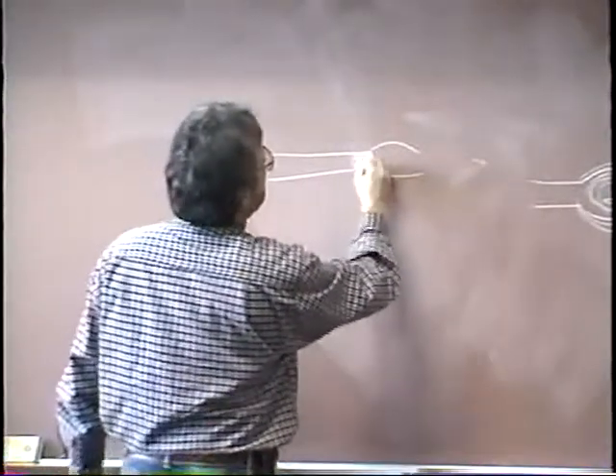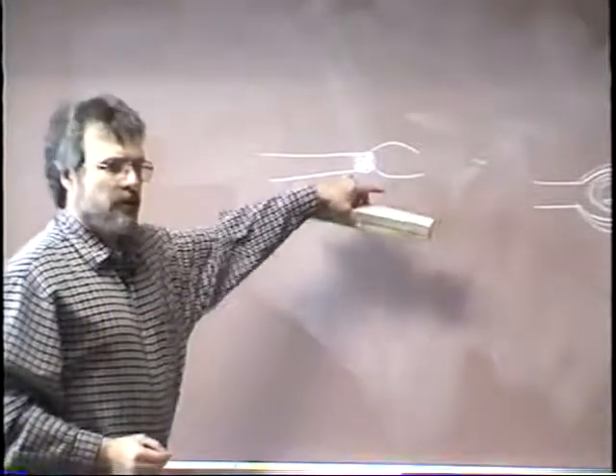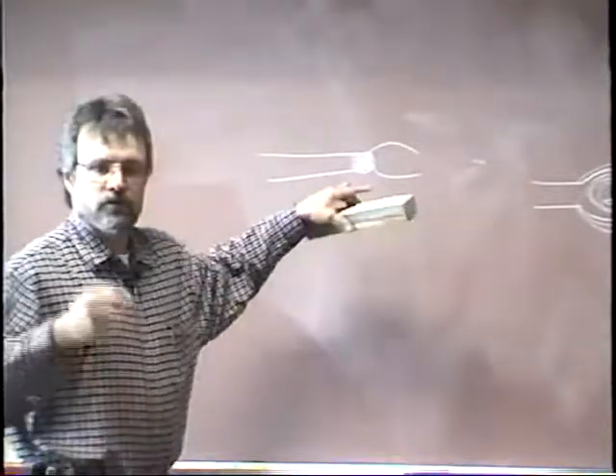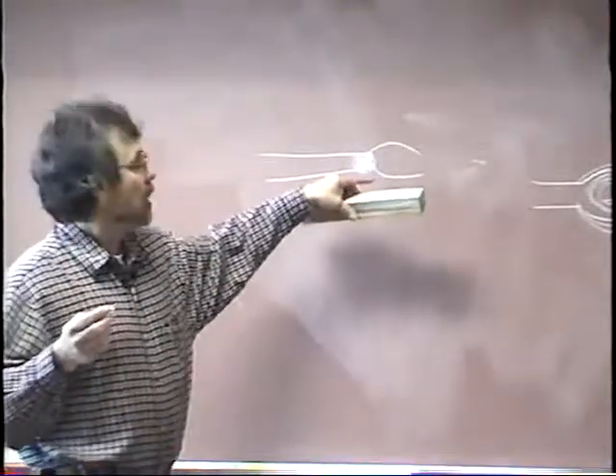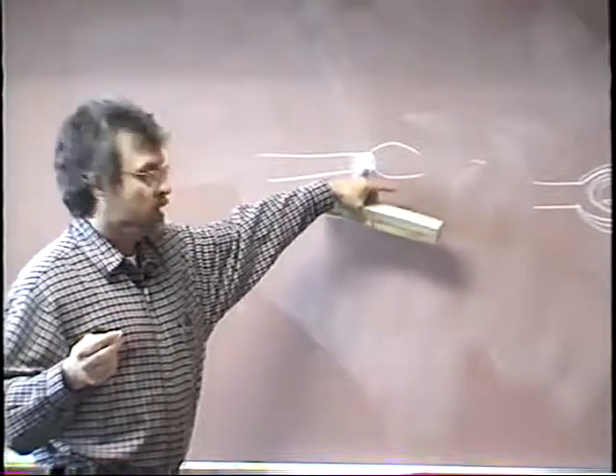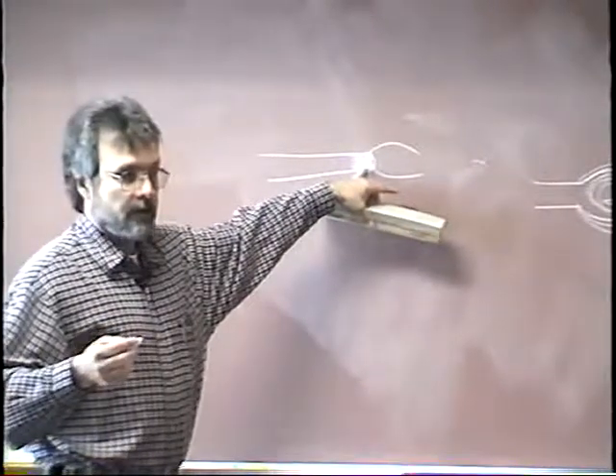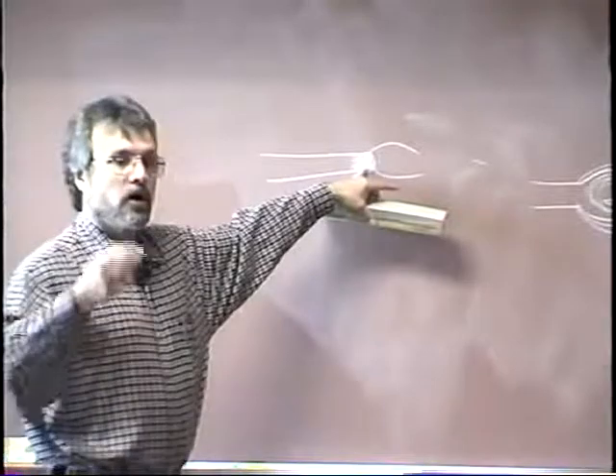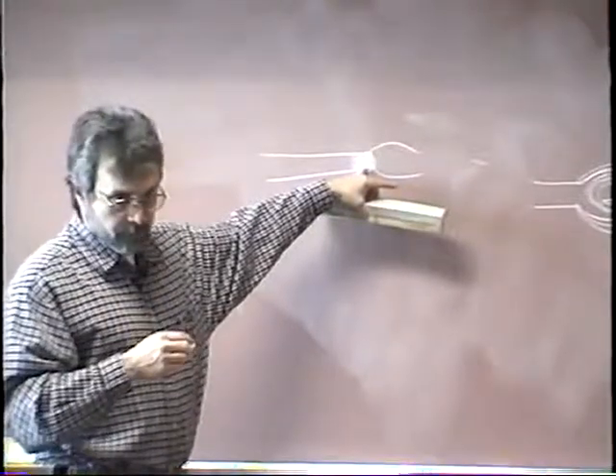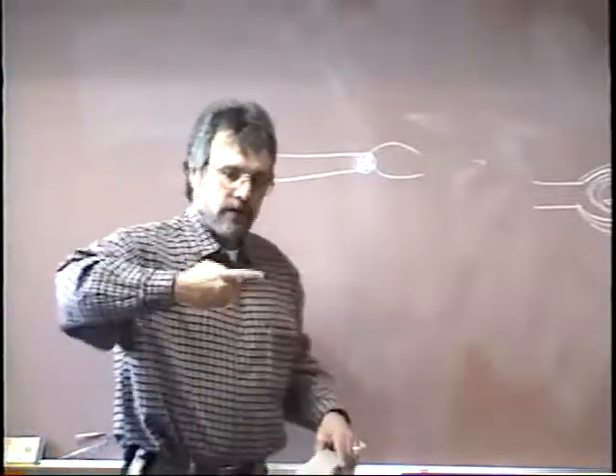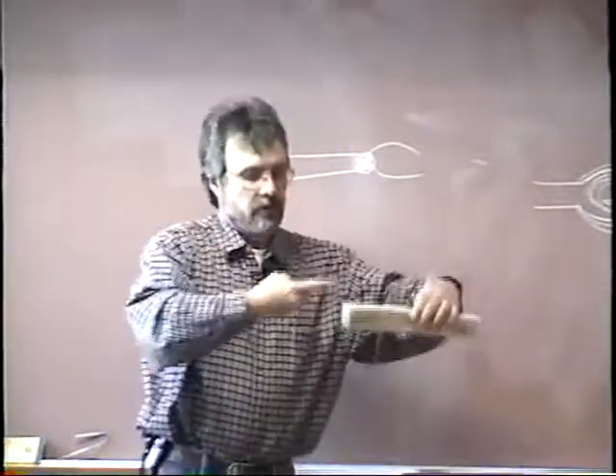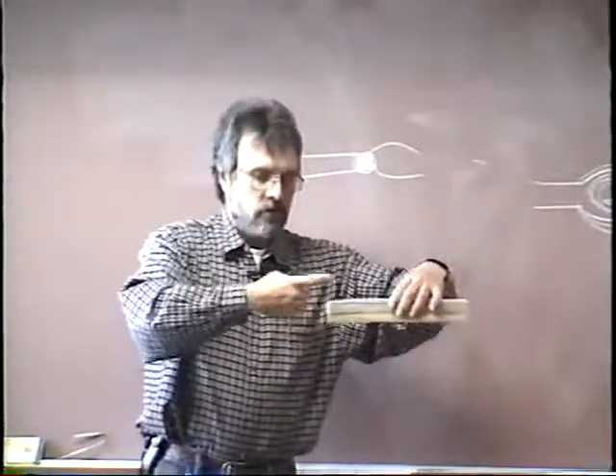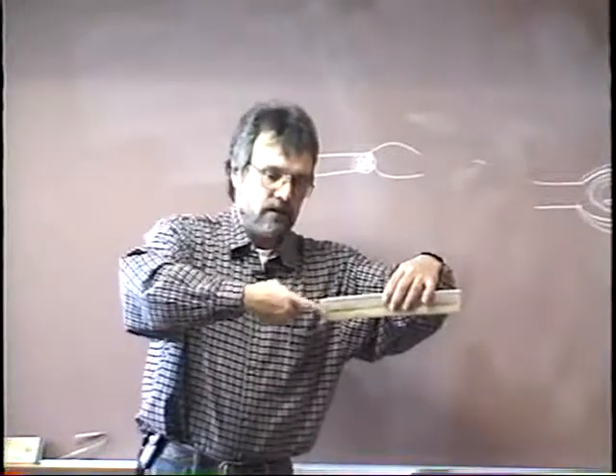And the whole idea here is you pause right on the edge of that weld, whether it's not your tack, but on a restart, you're going to pause right on the edge of that weld. And the idea is to sit there and let the heat from the arc melt where you left off. And once that has melted off, then think of that welding electrode as a hot knife slicing through butter. And this is your weld bead. And you want to take that and you want to slice right through the end of it.